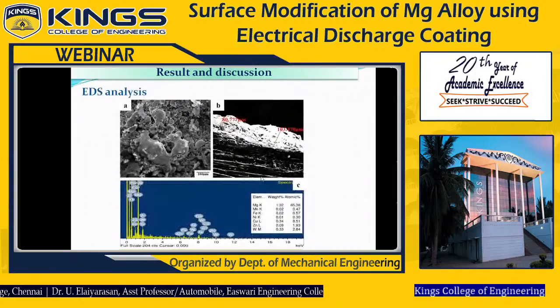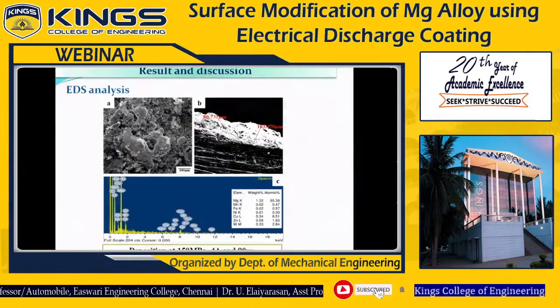Then, result and discussion. After coating, EDS analysis is very important. Energy dispersive spectroscopy analysis is used to identify the elements present over the surface of the workpiece after EDM. This surface is analyzed by the EDS analysis, and the corresponding layer thickness has been identified. Two different places were measured. One place is 80.77 micrometer, and the other side is 103.470 micrometer. So the average value has been considered in this study.